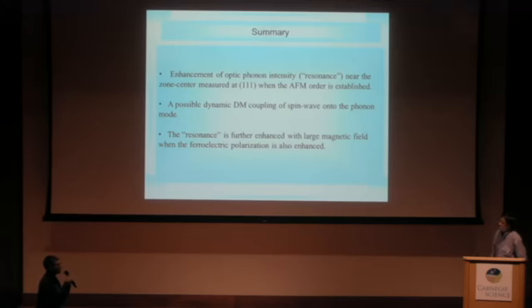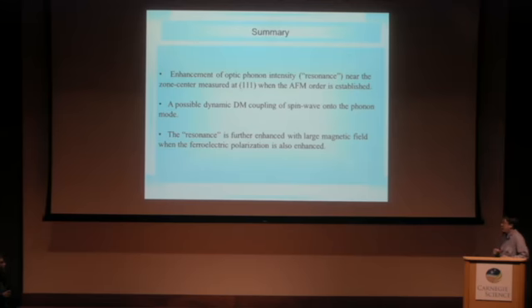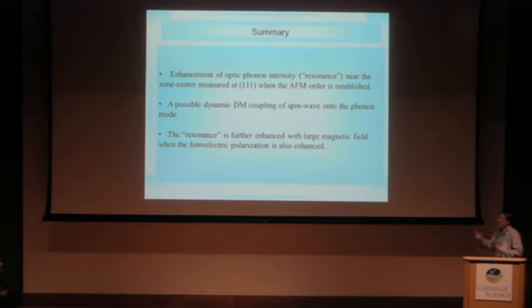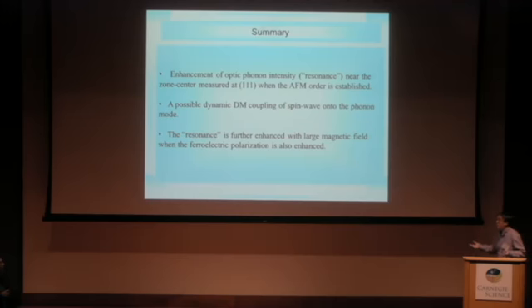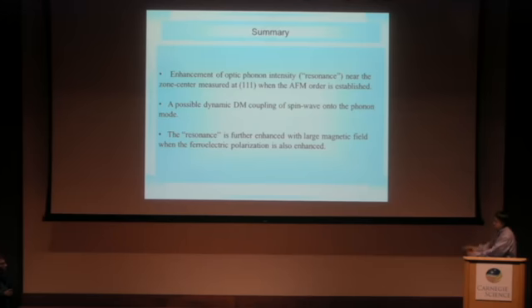Question: Did you try to calculate the dynamical structure factor—the phonon intensity—considering contribution of magnetic scattering in your experiment, or just nuclear scattering? Reply: We didn't do that, because I cannot find any reason why the enhancement would appear only at Q=0 and not away from it for that mode. If it were a structure factor issue, normally you'd expect at least a large part of the branch intensity to increase. I truly believe the enhancement itself is purely nuclear, even if it's induced by magnetic scattering.